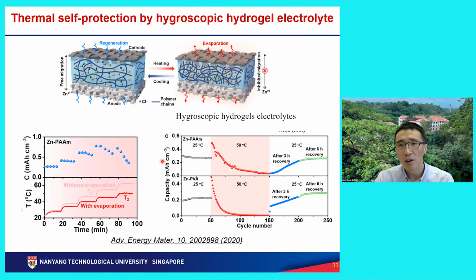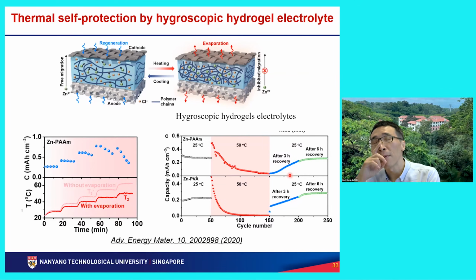So the idea is like this: you first charge the battery at 25-degree room temperature. Then we put the battery at a high temperature, 50 degrees. Not that high, right? If you go even higher, then the effect will be more obvious. So the battery capacity increases first, but then decreases very sharply after some cycles. Okay, it's not dead. It's just asleep. Then if the temperature goes back to 25 degrees, after a 3-hour recovery, the battery comes back to life. Maybe after 6 hours, it fully comes back to life. So you can see, the response is quite slow.